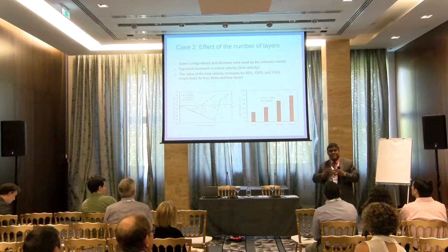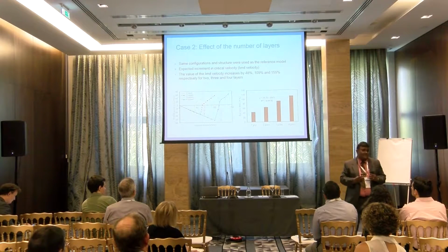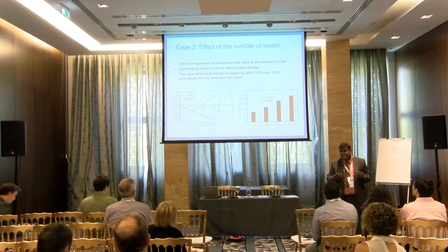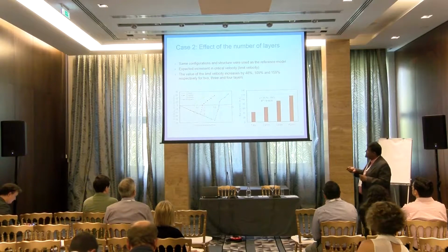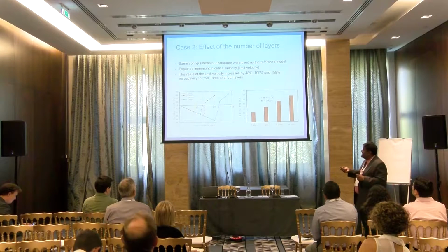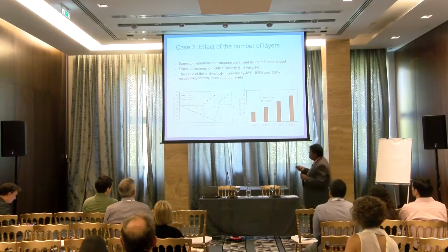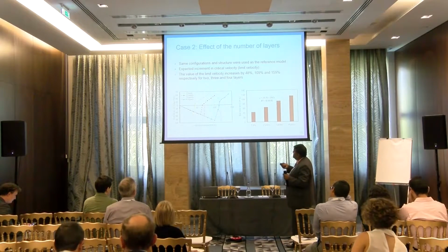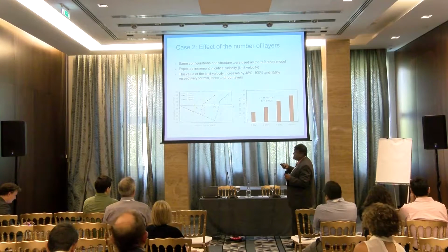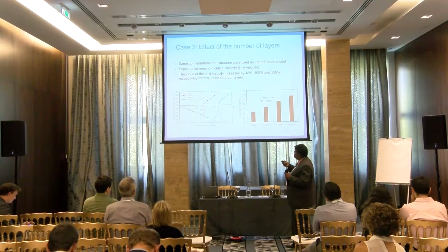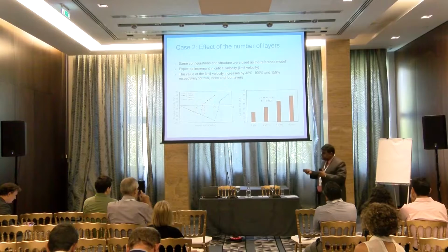a number of fabrics, and we can then orient the architecture, which we haven't looked at, but we just looked at what happens if you include 1 fabric layer, 2, 3, and 4 fabric layers, and how it affects the response. The response is very expected. For a 1-layer fabric, you can see the sudden damage or penetration starts at a very low velocity. It is 44 meters per second, and then at this point, which is a kind of limiting velocity of 46 meters per second, the projectile penetrates through the fabric.